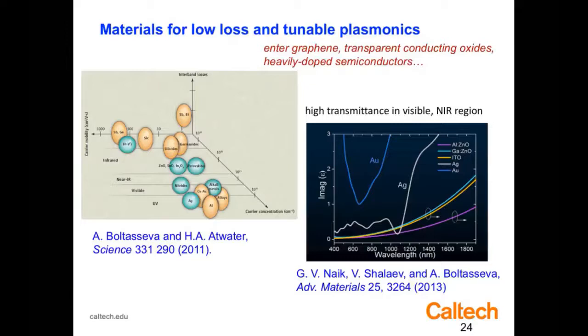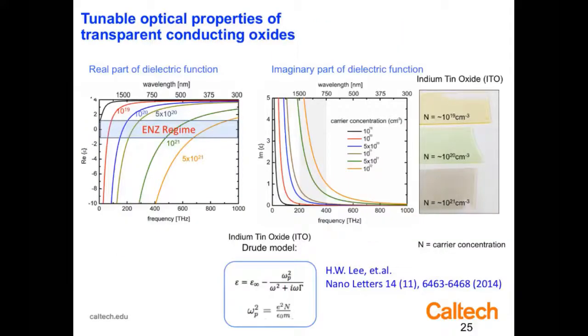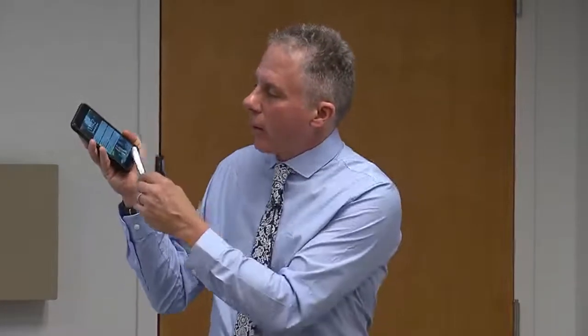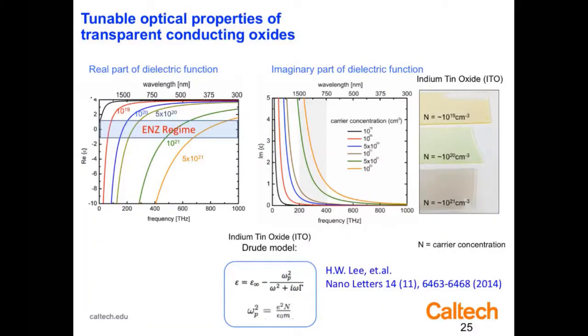Okay, so here's an example of a material that you all have. I feel virtually sure that everybody in this room owns a piece of indium tin oxide. How many people have one of these? The surface of the screen is coated with a semi-transparent conductive layer of indium tin oxide. And you can see here, the carrier density is relatively low because it just has to act like a DC conductor. If I crank it up a little bit to 10^19, to 10^20, to 10^21, you can see by eyeball spectroscopy, basically it's changing color a little bit.